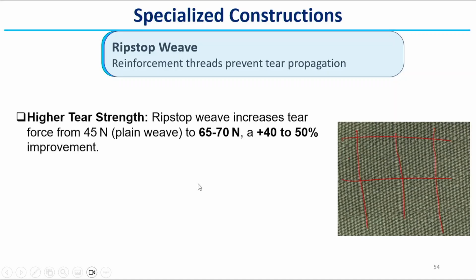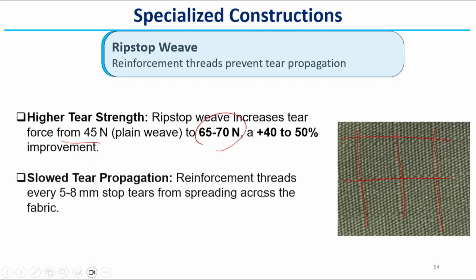Higher tear strength: ripstop weave increases the tear strength, tear force from 45, it can go up to 65 to 70. So, 40 to 50% improvement in tear strength only by incorporating the reinforcing threads. Slow tear propagation: reinforcement threads every 5 to 8 millimeter stop the tear propagation.